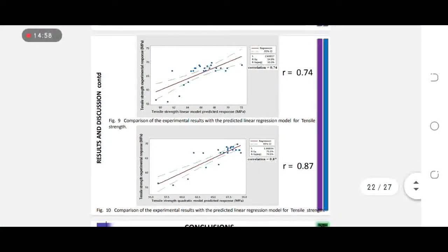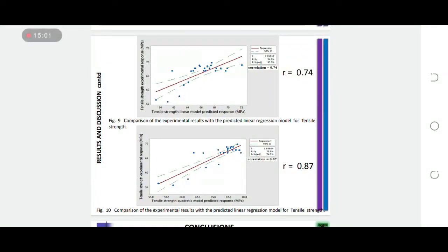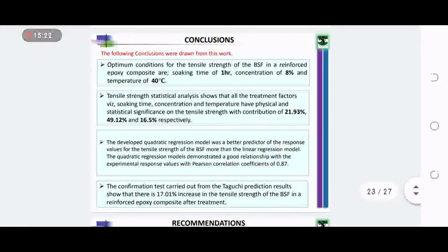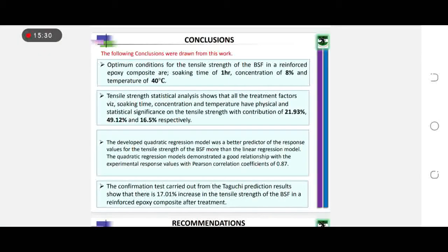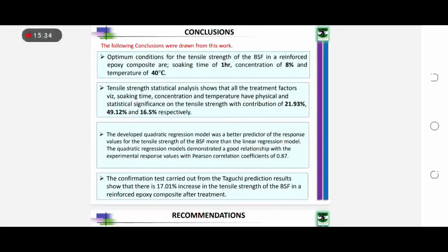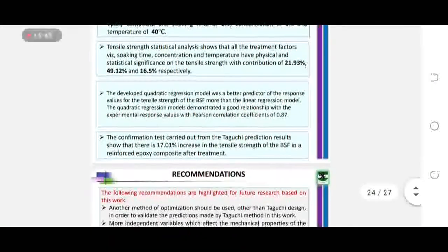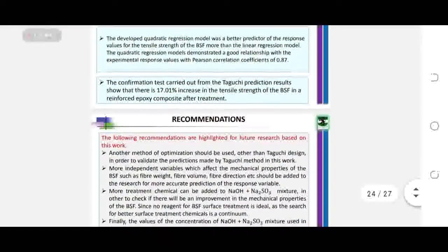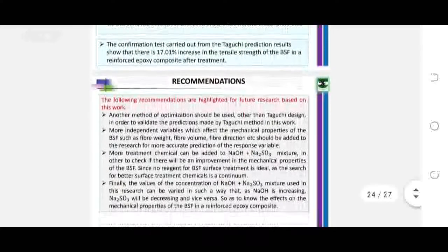We see that the comparison between the two shows that the quadratic regression model we generated is predicting better, with a Pearson correlation coefficient of 0.87, more than the linear regression model. We concluded that the optimum conditions for the tensile strength of the banana stem fiber composite are a soaking time of 1 hour, a concentration of 8%, and a temperature of 40 degrees. The tensile strength ANOVA analysis shows contributions of 21.9% for soaking time, 49.12% for concentration, and 16.5% for temperature. The developed quadratic regression was a better predictor, and the confirmation test shows that there is a 17.01% increase in the tensile strength of the banana fiber after treatment.